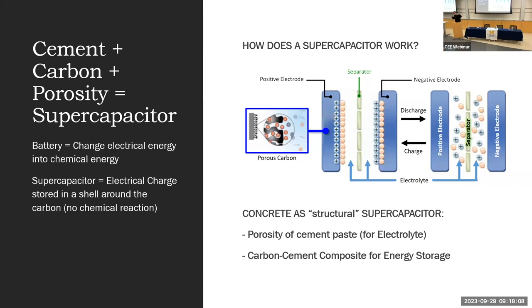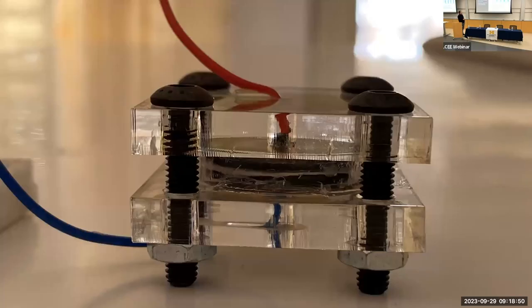In the moment when you have made it, bringing this hydrophobic material into this alkaline hydrophilic environment of cement and let it hydrate, what you need there is the electron conductive cable, which is basically a volumetric wire. What you need is the porosity, which is naturally created in cement-based materials. And you need a large enough specific surface in the carbon black, the so-called storage porosity, in order to store along this volumetric cable all the energy needed.